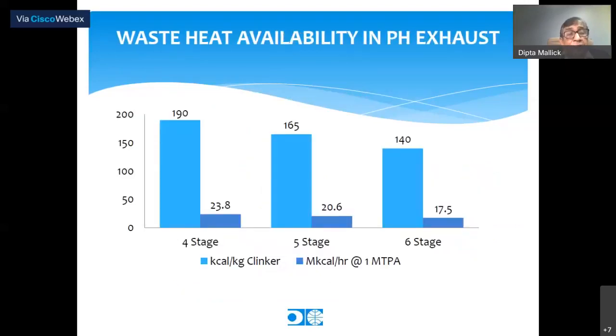The amount of energy available for a 4-stage preheater is about 190 kilocalorie per kg. More stages mean more heat transfer in the preheater, and therefore less heat liberated through the preheater. So a 5-stage gives 165 kilocalorie per kg, and a 6-stage gives 140 kilocalorie per kg. Even this figure is quite high. Please, next one.